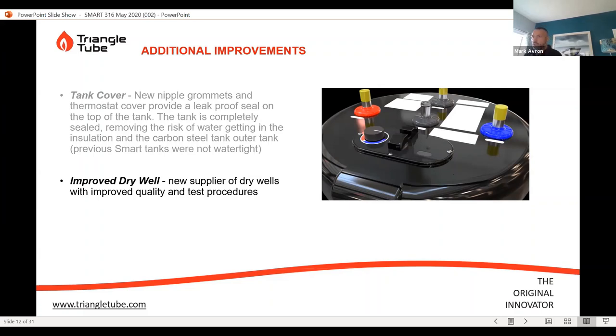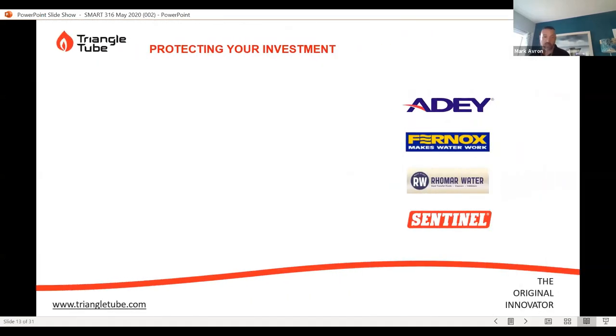So, improved dry well. We've gone through a period where we had some leaks on the dry well on the tank, which caused problems, obviously. So we've gone to a new supplier to produce the well for us, and we also have a testing procedure where we're testing the integrity of every well before it goes into the tank. Dip tubes are now, and they have been for a while, but just to point that out, made out of a PEX material, so they're very strong and corrosion resistant.